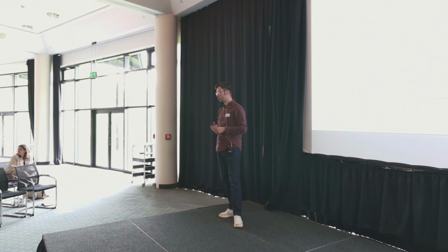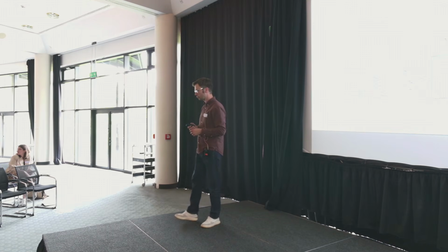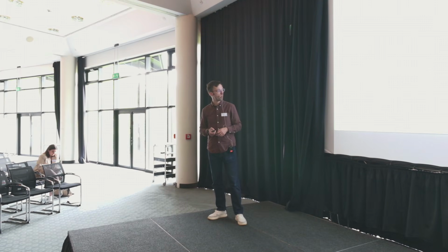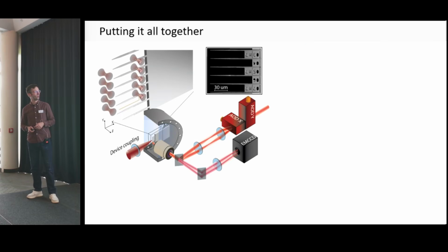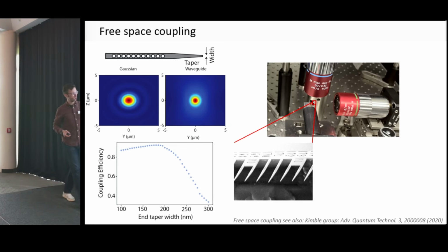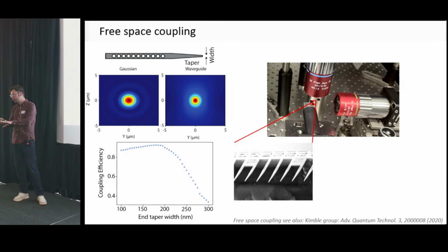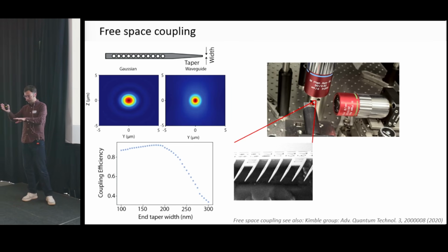There's another question over there. So thanks for the nice talk. Regarding the cavities, did you undercut them or remove the material for coupling? And how reliably does this work for you? Wow, okay. So you're doing fab? Personal problems, let's say it that way. We do undercut it. So here we do a combination: we first fabricate the devices in the middle of the chip, then we dice it, and then we do KOH etching to make them freestanding.